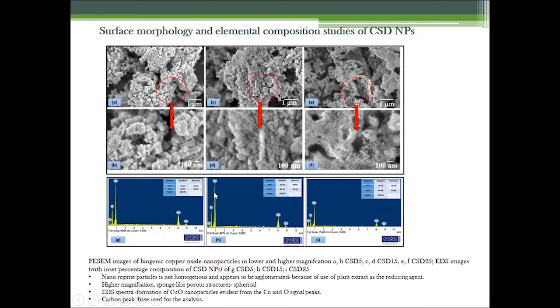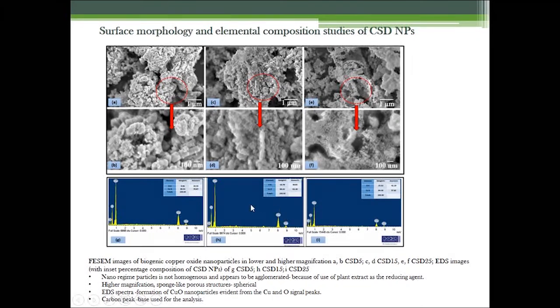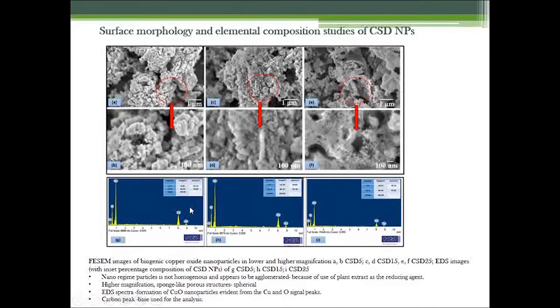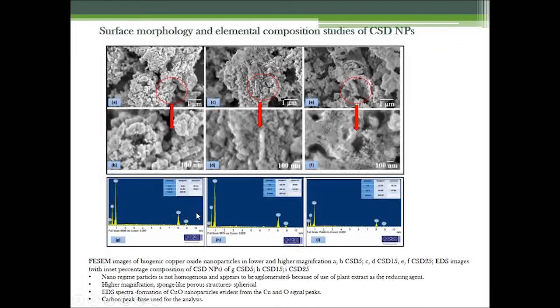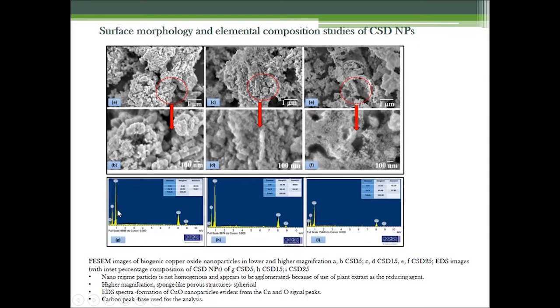These are the EDS spectra of the nanoparticles synthesized, which confirm the formation of copper oxide nanoparticles, evident from the copper as well as oxygen signal peaks along with the carbon peaks. You can observe the carbon peaks also in the following image, which is due to the base used for the analysis, and also because of the presence of phytochemicals.